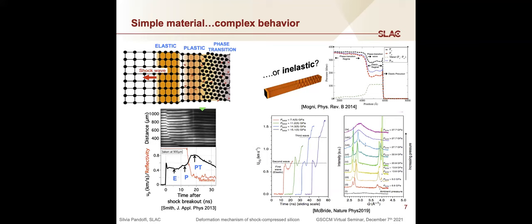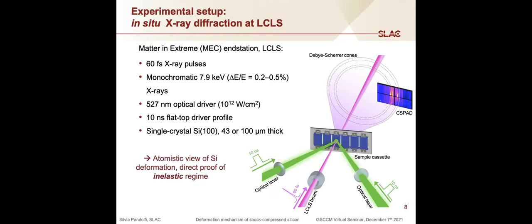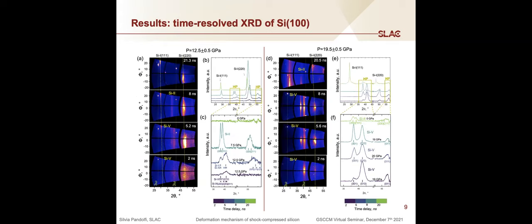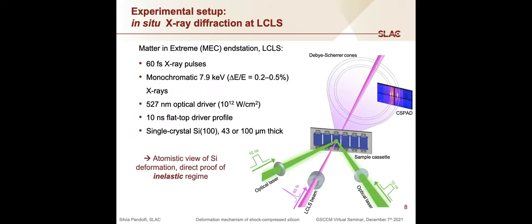However, because we're using a single crystalline sample, we don't really have this problem, even if we are in a collinear geometry. When we start with such perfect single crystals and we have this highly monochromatic X-ray probe, we don't see the diffraction signal from the starting material. So we're actually able to see the signal only once there is some defects, some texture, some mosaicity to it.